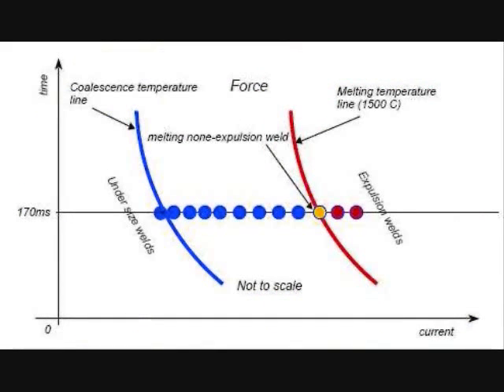We can use the data we did in experiment 1 to plot it on a weld lobe. It will look like this picture. There's one undersized weld which is less than 5 millimeter, then the rest are all solid state welds, good welds. The number 10 coupon is the yellow one sitting right on the edge of the melting temperature. And on the right hand side of the red curve, we have two expulsion welds. When we understand expulsion weld is not repeatable and not controllable, we can then start making more and more solid state welds.